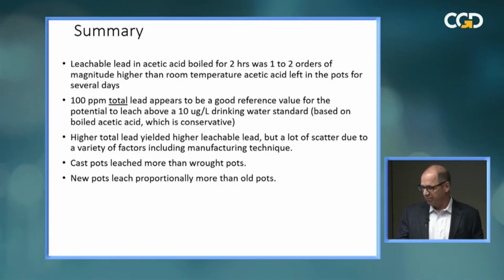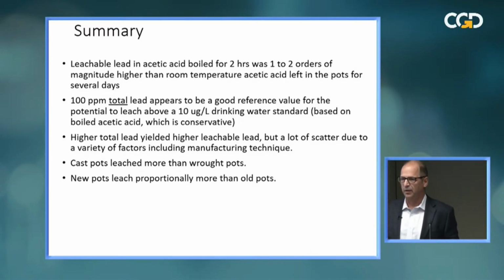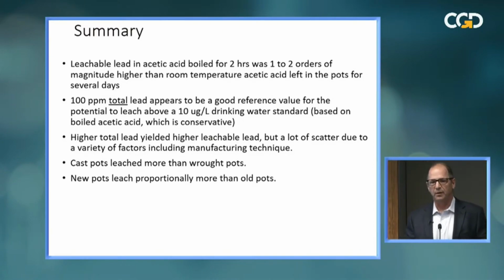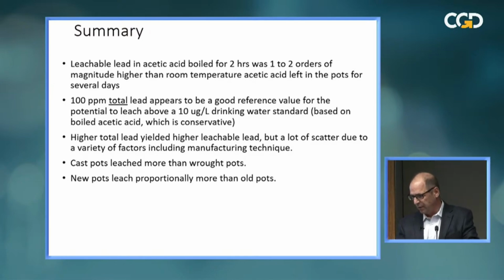In summary, heating was really important to leaching, 2 to 3 orders of magnitude higher. This says 1 to 2, but that's a mistake. Our 100 part per million level for a significant contributor to leachable lead in the leachate, I think, is a good one. And generally, yes, pots with higher total lead tend to leach more. Cast pots leach more than the wrought pots, and new pots leach more than the old pots.